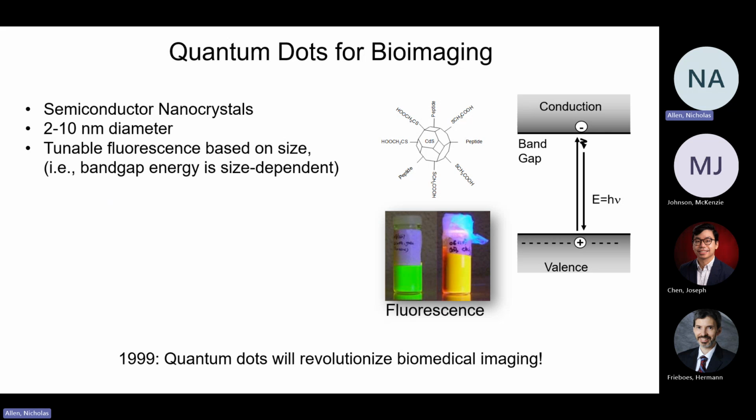Let's get to that. So they have tunable fluorescence based on size. If I change the size slightly, the color changes. So that gives me a lot of control over the different colors. Whereas for a fluorophore, I have to chemically modify the fluor to get a different color. So it's a lot more difficult to get a color panel. They can all be excited by the same laser. So for the fluors, for each color, I might have a different laser. So I have 9 different lasers to get the 9 different colors. That's time consuming because it takes time for each laser to flash across that cell. Here you could do everything with one. So that will cut time.